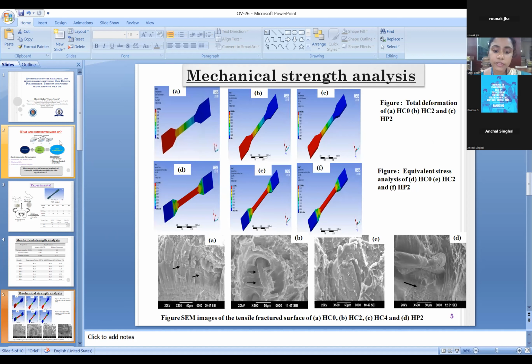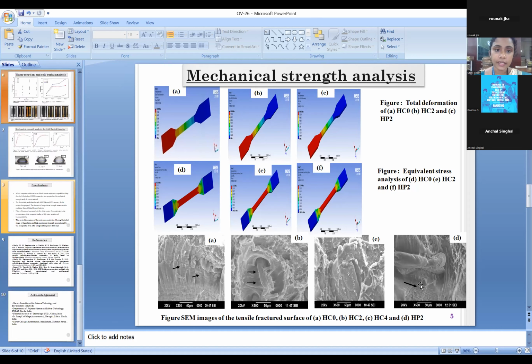The images of the tensile fracture surface were also taken. Here we can see that at zero concentration of chitosan, a wave-like morphology was obtained for the system. This indicates the ductile nature of the composite. When varying concentrations of chitosan were added, this morphology was disrupted. At higher concentration of chitosan, agglomeration has started to take place. And when palm oil was added to the system, the wavy nature was regained, which shows that the system has again attained the ductile nature.